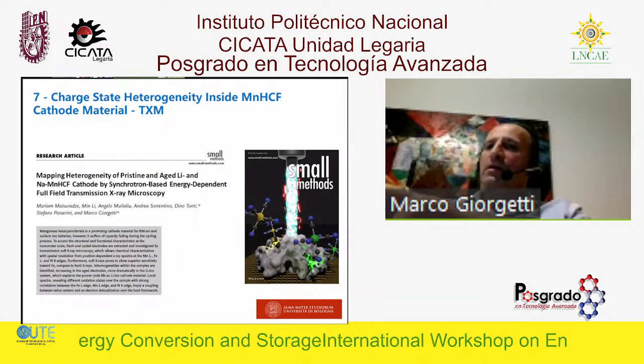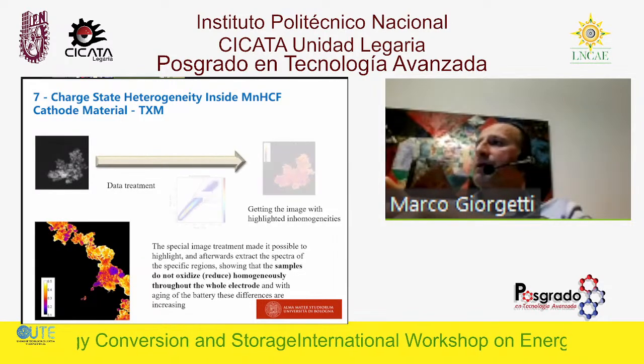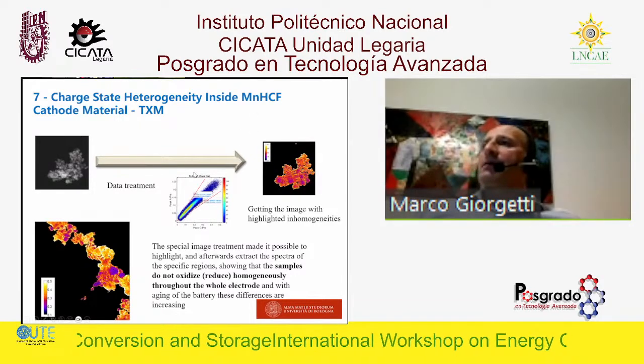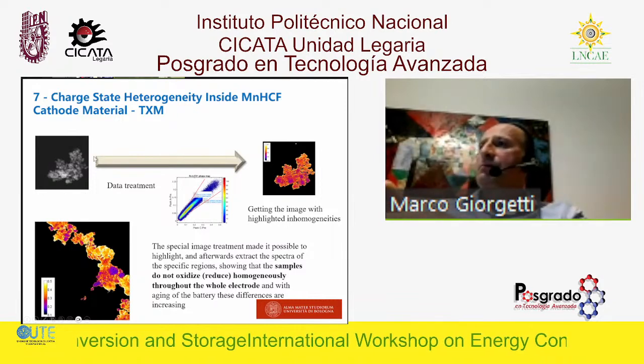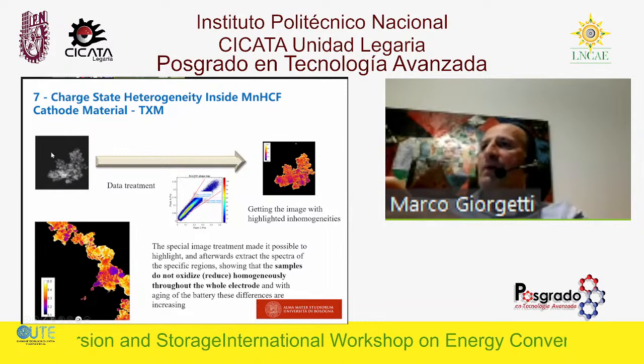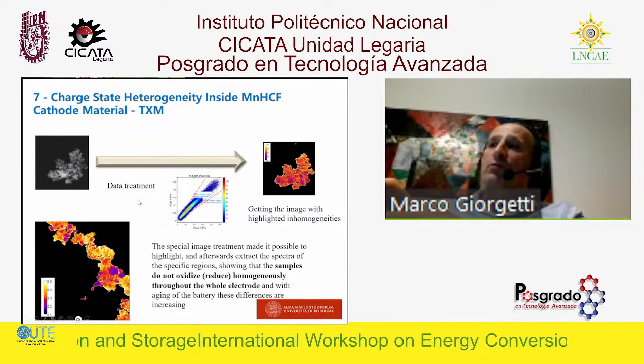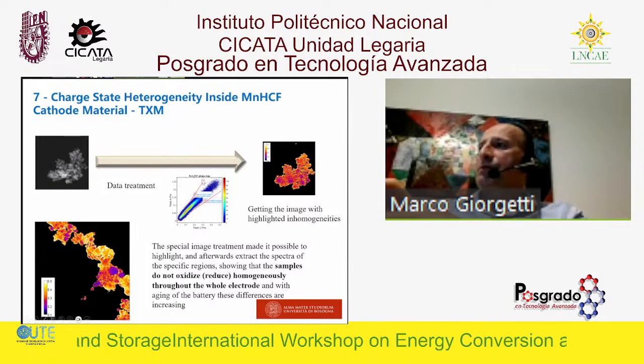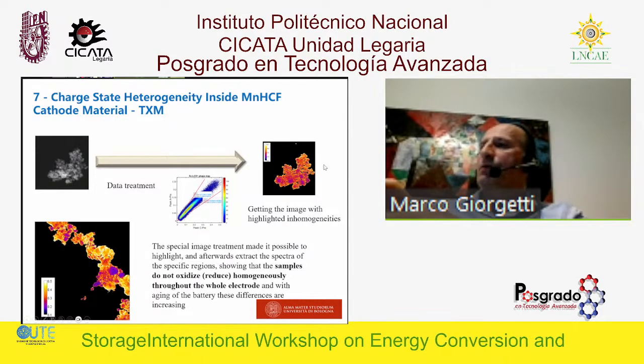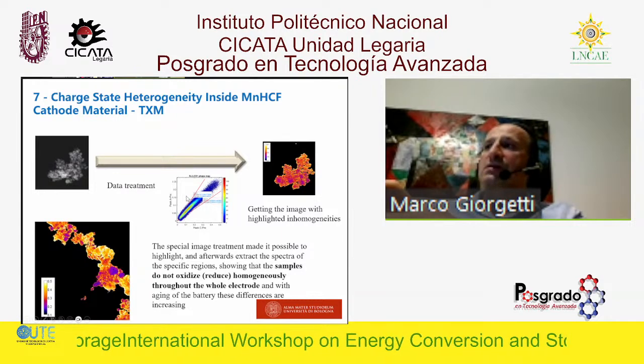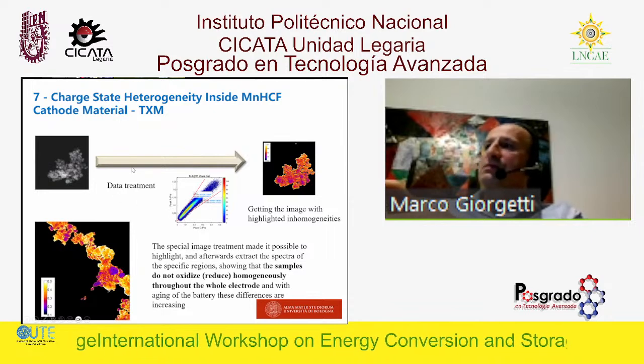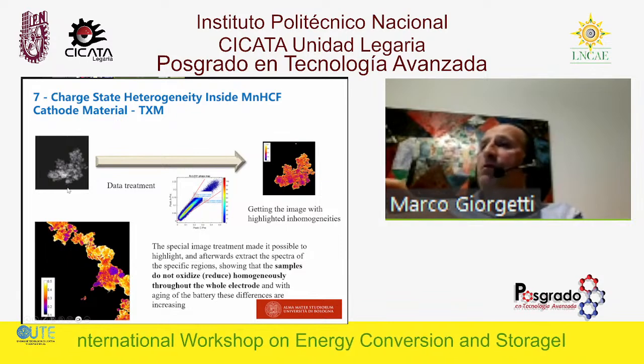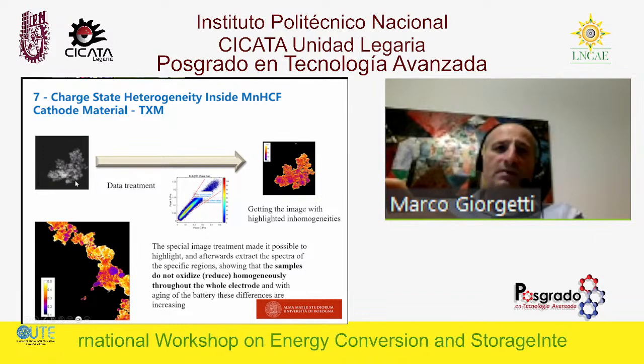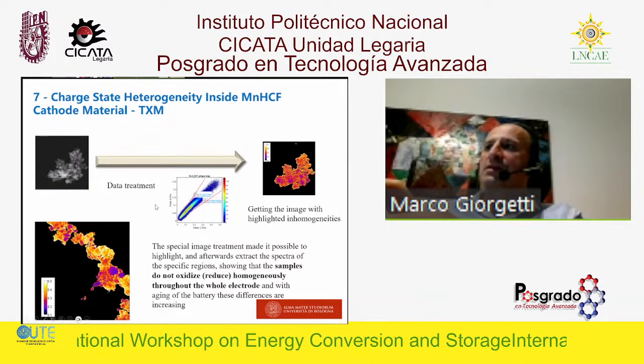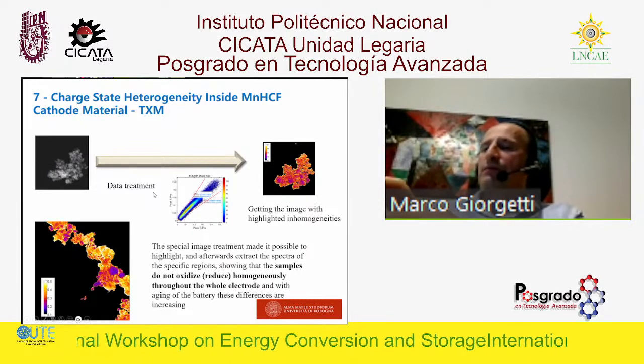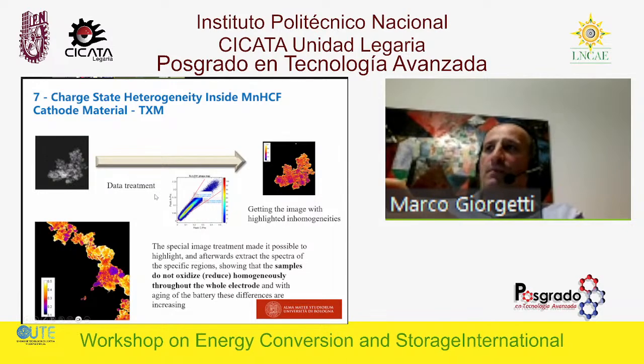Another view of the microscopy was this one. Okay, this is just the information that you can get from TXM. Of course, we need to do a lot of data treatment. I won't be tedious here, but basically when you get the images, different colors mean different homogeneities. The very difficult thing here is to produce an image from this point, because you have to normalize, since the thickness is not exactly the same in all the particles. You have to find a way of normalization, with a lot of data treatment, to get rid of the pitfalls due to different thickness in your samples.